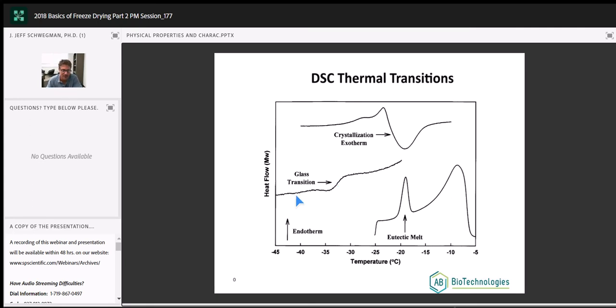Okay, now you'll notice the noise in this baseline is very noisy compared to the others. That is because we've had to magnify this transition to get it to show up with these other transitions. It's a very low energy thermal event. Think about it. When we go through a eutectic melt, we're breaking bonds, tearing crystals apart. Thermodynamically, it's a pretty high energy event.